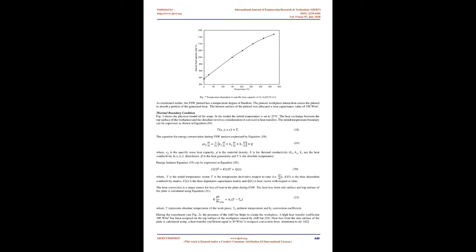In the model, the workpiece is considered as a solid ductile material whose constitutive model is capable of large strain, high deformation, and Johnson-Cook strain hardening effect. The workpiece's material behavior was considered to be dependent on the rate of strain, which was determined after reviewing the pin tool rotational speed and travel speed of the FSW schedules covered in this research. As referenced before, there was no external heat source input applied to the model, rather heat generation in the model was a result of friction work between the tool and the workpiece interface.